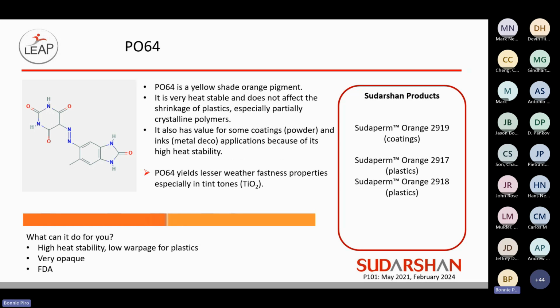Orange 64 is a very yellow shade and very opaque pigment with great heat stability for plastics. It does have, again, for the same reasons, that high heat stability. It has value for powder coatings as well as potentially metal deco inks where those temperatures can be high. Pigment Orange 64 has less weather fastness properties than the other orange, the Orange 36, which will be next, and especially in tint tones. So something to consider when looking at oranges in this space. So it's very opaque and has great heat stability as well.